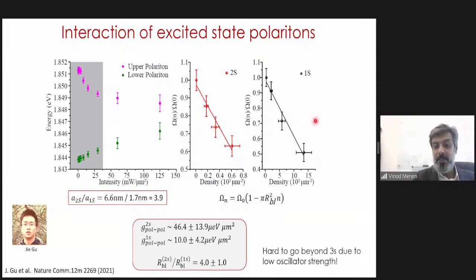So we are comparing these two systems, and you look at the densities, and you will see that the densities at which you're getting these shifts are almost an order of magnitude smaller than what is needed for the 1s. In other words, if I look at the interaction strengths of the two, I get a scaling factor of about 4, which is roughly the ratio of the Bohr radius between the two. So this was a nice exercise in proving that going to excited states can give you an enhanced interaction.